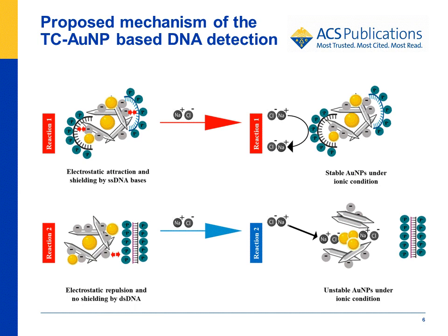In case of unhybridized single-stranded DNA, it is believed that the negatively charged phosphate groups of DNA are distanced from the TC-AuNPs by the electrostatic repulsion between the negatively charged AuNPs and phosphates, while the nitrogen bases are oriented towards the charged AuNPs through attraction, leading to the formation of a protective DNA layer. This layer acts as a barrier for NaCl and prevents the destabilization of TC-AuNPs.